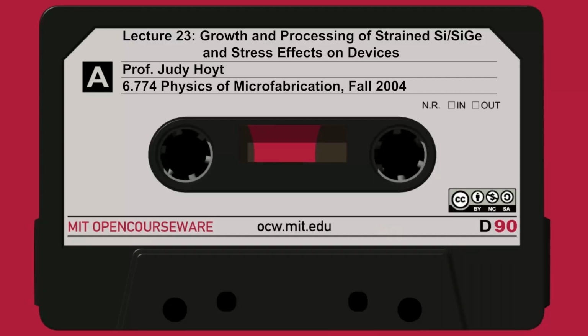This is the effective equilibrium diffusivity, so it's the diffusion coefficient in centimeters squared per second as a function of inverse temperature, the usual kind of Arrhenius plot. The dashed line here is for diffusion in silicon, and the solid is for diffusion in silicon germanium. If you look at boron here, in fact, in 20% silicon germanium, the diffusivity is reduced. I'd said before a factor of 10, looks more like a factor of 6 or so, depending on the temperature.